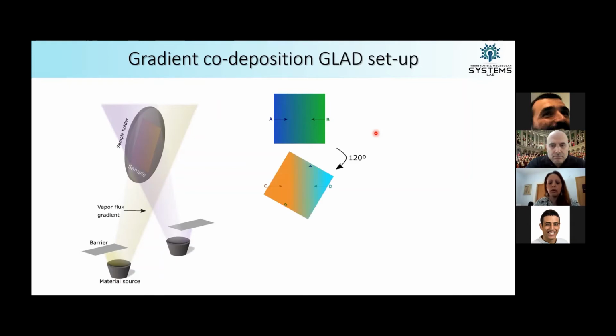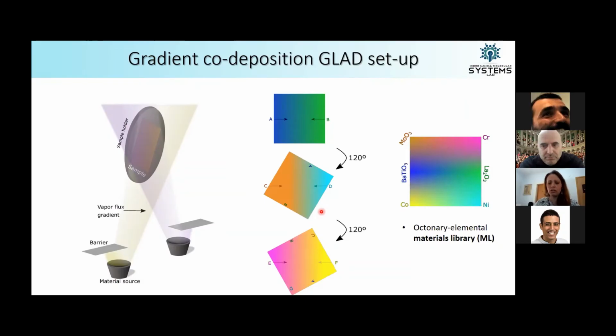So we then rotate this sample by 120 degrees, deposit two more materials in a binary system, and rotate it again and deposit two more. So we end up depositing 6 different materials at 3 different phi angles, so rotation of the substrate around itself at the same alpha angle tilt. And this leads us to an octonary elemental materials library. It's octonary because some of the material sources had 2 or 3 different elements in them.